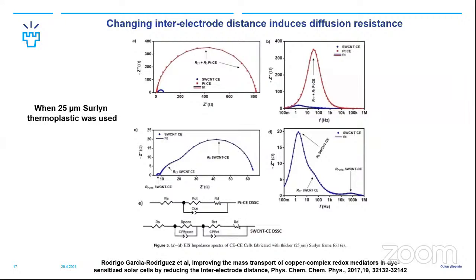Are we just aiming for a reduced Z prime, the real part of the impedance? Let me explain it to you. Typically, when you work with the platinum counter electrode catalyst materials, you always get mostly three impedance arcs. But here you can see only one big arc, merged, because of the diffusion resistance and the very large charge transfer resistance, it was very difficult to separate them out.